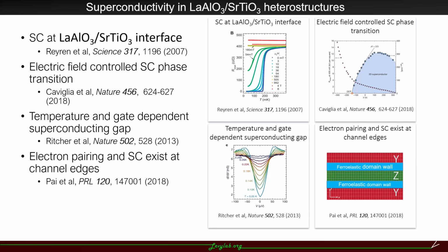There are many hypotheses on the superconducting mechanism. One of them is ferroelastic domain. It has been demonstrated by Pai et al. that electron pairing and superconductivity exist at conductive channel edges, which are also ferroelastic domain walls. To further explore why this heterostructure is a superconductor, we combine this material with strain engineering techniques.